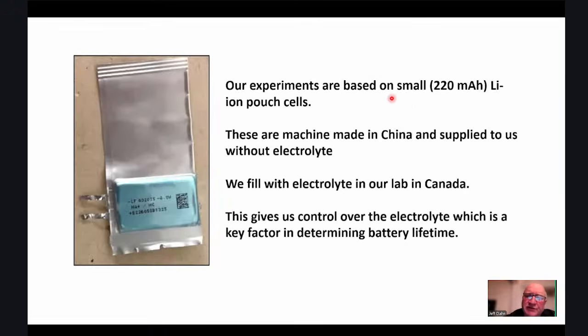So I'm going to show you data on experiments that are based on small lithium-ion pouch cells. They look like this. It's about 4 centimeters along the direction my laser is moving. And these are machine made in China and supplied to us without electrolyte. And we fill with electrolyte in our lab in Canada.